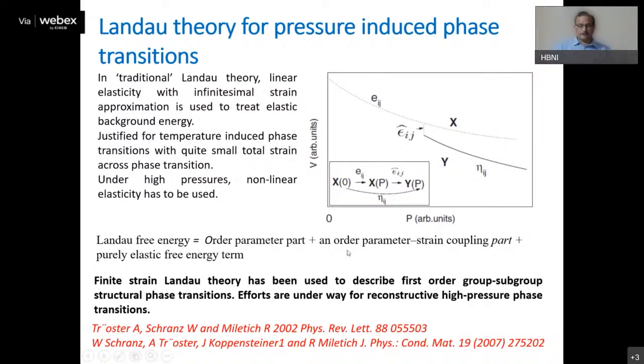So basically, as we discussed earlier, in case of external field, we have a Landau free energy which is based on the order parameter, basically higher order terms of the order parameter. And then we have some correction to the free energy corresponding to the coupling between the order parameter and the external field. In the high pressure case, we have to add one more part, which corresponds to the elastic free energy corresponding to the first phase.